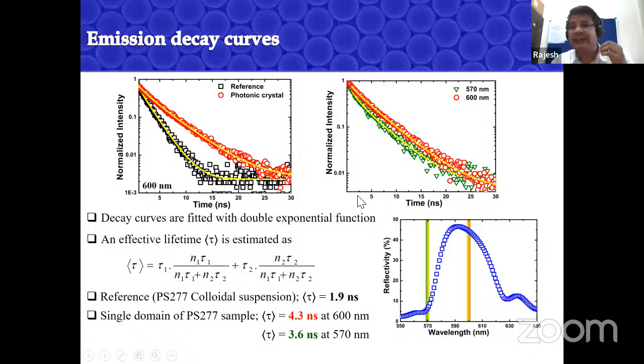Okay. And then we measured this decay rate from the photonic crystal, which is emitting at the band gap. And what you see here is the emission decay is quite slowed down. It doesn't come down fast like this. It's quite slow actually. And then you fit that, and you get a lifetime of around 4.3 nanoseconds. That means the intrinsic lifetime of your emitter is 1.9 nanoseconds. By putting it within the band gap and emitting within the band gap, the lifetime becomes 4.3 nanoseconds. The lifetime is increased. That means it stays in the excited state for longer than it's supposed to. And that's because there's no way it can come out. Now you may ask why it is not infinite. Because these are real samples, there is always some pathway it can connect to the outside world because of the unwanted light scattering and all.